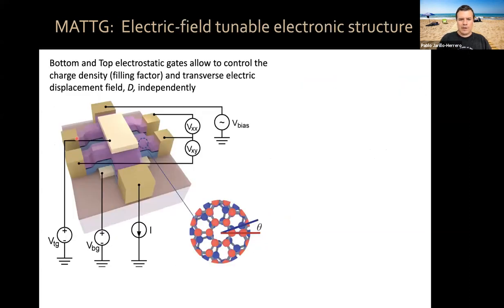Now, in our devices, we have our magic angle twisted trilayer graphene in a Hall bar geometry, with source and drain contacts and Hall voltage, Rxx and Rxy contacts. We also have a bottom and a top gate voltage, so metallic plates. With those two metallic electrodes, we can apply symmetric or anti-symmetric voltages so that we can vary independently the density of charge carriers in the magic angle trilayer graphene, and also independently the electric displacement field in the vertical direction, so we can polarize carriers in our structure.